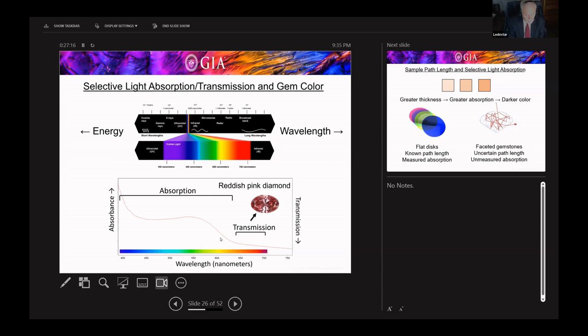Most gems are colored by what's called selective absorption. So on the bottom, I have one of these absorption graphs with absorption going upwards, shown on the left-hand side, and transmission increasing downwards. And I show the visible spectrum from about 400 to 700 nanometers, and from about 400 to 650 roughly, or 600, the light is being absorbed as it passes through the gemstone. What is being transmitted is the red colors, and that's what your eye sees, the pinkish red color of this diamond. So it's the idea that color in most gems is the result of selective absorption or selective transmission of light as the light passes through the gem material.